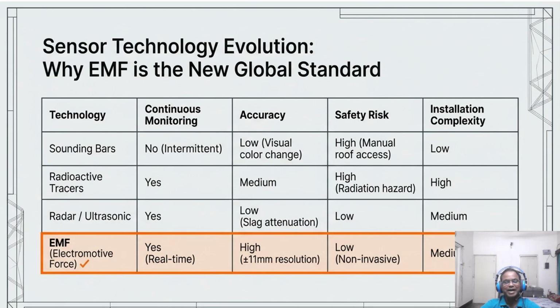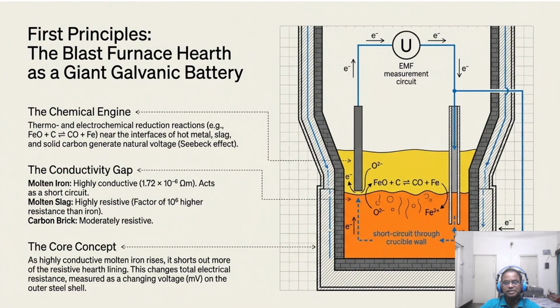So now let's look at the math that translates those chemical reactions into actual numbers. How do we translate chemistry into voltage? We use the Nernst equation. Here E is the raw microvoltage we capture at the shell. It is strictly governed by the absolute temperature of the melt and the oxygen activity, or PO2. So essentially every millivolt we measure is a direct, mathematically predictable output of the oxygen activity and temperature interacting with your lining. With this math in hand, we can follow a simple three step master class to get our final reading.